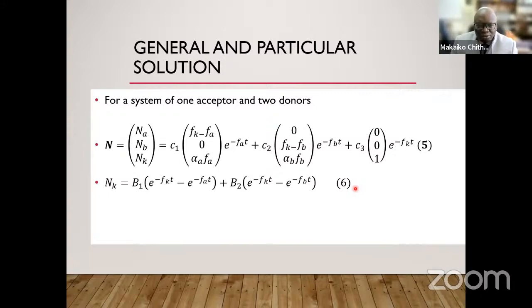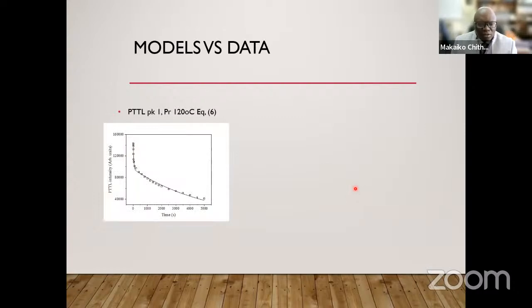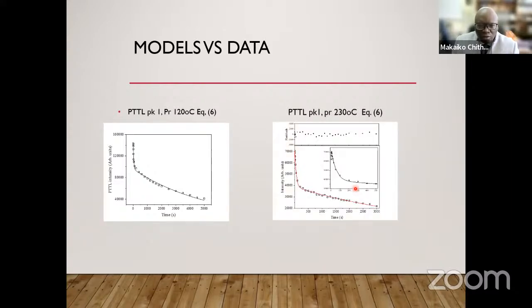Okay, so let's see how well this applies to tanzanite. Let's compare the model and experimental data. Peak 1 after preheating to 120, 1 acceptor and 2 donors. We can see that the model describes the experimental data quite well. Peak 1 after preheating to 230. You have one donor, and again, you can see that the model describes the experimental data very well. This is also reflected in the residuals just above the curve there.